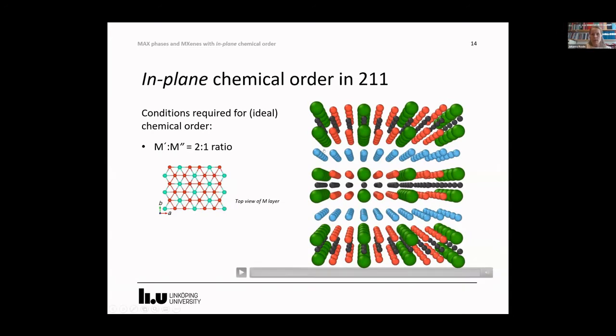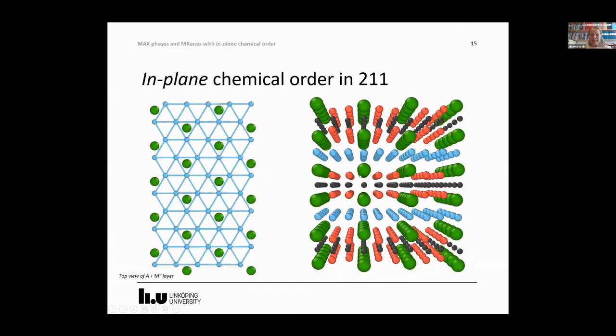But the energy for this structure, when not relaxed, is very high, so the phase is not stable. But the energy is drastically reduced if we allow an atomic size of the alloying element to be larger than the M element, and if we allow relaxation of the structure. If we start by relaxing the metal carbide layer and you look at the green atoms, you see that they will extend from the M layer towards the A layer.